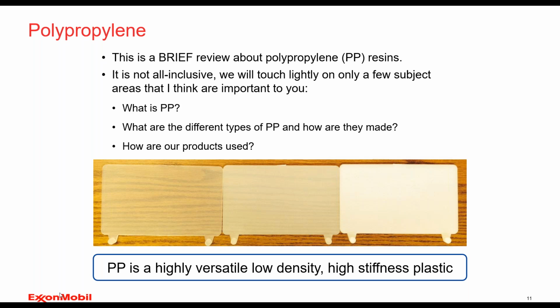If we look at this picture here, we can see these resins in their natural form, and it can quickly remind us who work in plastics all the time but may not see the natural state, that you can quickly identify the three different types of polypropylenes. The random on the left is clear. I'll note that these plaques are thick at about 100 thousandths thickness, and what you can see through it has good clarity and good contact clarity. You can see the wood grain through that plaque, and that plaque's on the left.